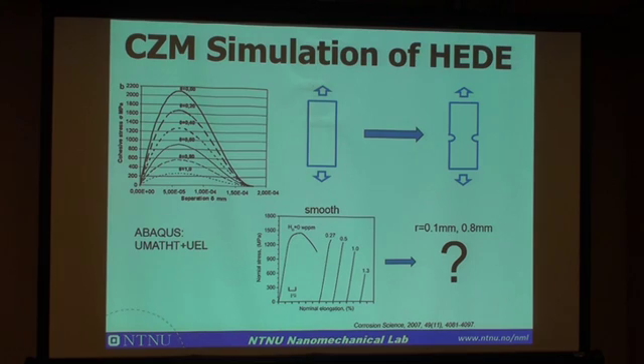Finally, I would like to introduce some new results on the hydrogen embrittlement simulation of high-strength steels. Now it's quite a common practice to simulate the hydrogen-enhanced decohesion by cohesive zone model. Here the vertical axis is the traction, that's the stress, and horizontal is the separation, the distance. This traction separation law is influenced by hydrogen. In the beginning, we have virgin material. If you have more hydrogen, this law will be decreased. And we can easily implement this cohesive zone together with hydrogen diffusion into a finite element model.